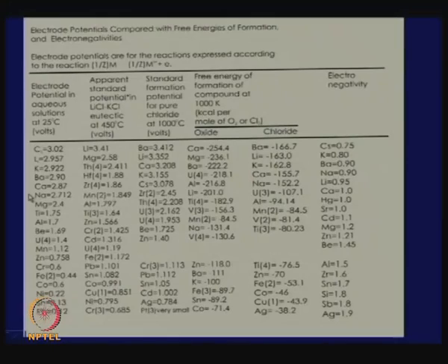This will be the basis of metallothermic reaction, to which I will come later on. So, what I am trying to say is, when you have a series like this which indicates relative reactivities, we can say that the metals placed higher above, being more reactive, will replace those below from their compounds, or replace hydrogen from aqueous media and dissolve themselves.